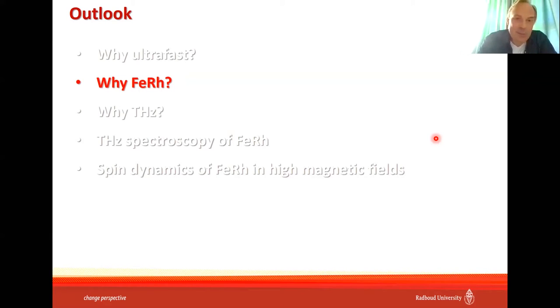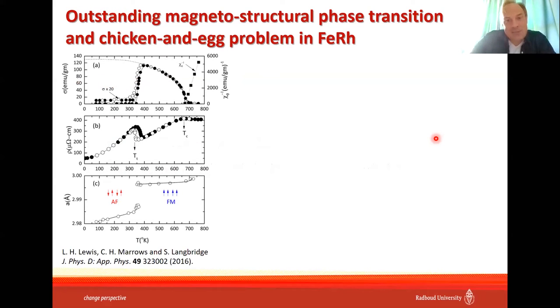So since that time, I always remember that probably I should say the existence of a material like iron rhodium is interesting in itself, and then still I would like to motivate the choice that we made. Why I find this material fascinating is that it has a very unique, I would even say outstanding, magnetostructural phase transition, which eventually makes us think about the chicken and egg problem. This material has a phase transition from antiferromagnetic to ferromagnetic state upon temperature increase. Normally our intuition expects that if you take a magnet and increase the temperature, you can only destroy magnetization. But if you take iron rhodium, at room temperature it doesn't have magnetization, but then you increase the temperature, and eventually magnetization appears. So what happens here is a phase transition from antiferromagnetic to ferromagnetic state. The phase transition happens not only in magnetic systems.